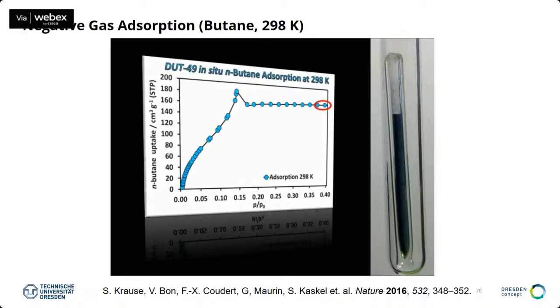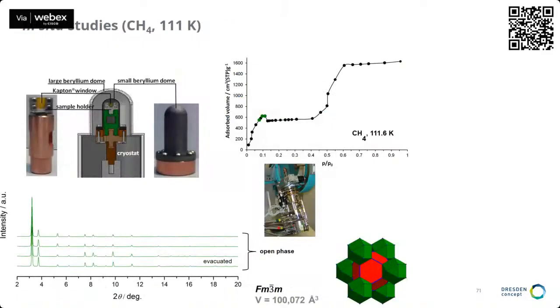So with the naked eye, you can see that there's a huge structural transformation happening in this kind of porous material. And of course, the naked eye only shows you the powder, but to get an understanding what is happening inside the structure, you need X-ray diffraction, for example, powder X-ray diffraction. And we did this with the apparatus that we had developed at that time. And before this negative gas adsorption step, you have a large pore structure. Here is the octahedral pore inside. You have a cubic structure with about 100,000 cubic angstrom in pore size.